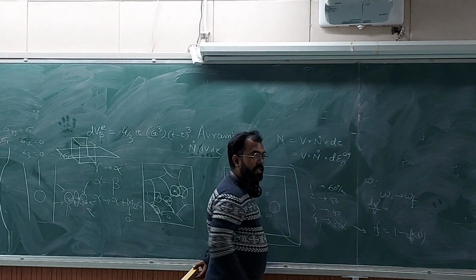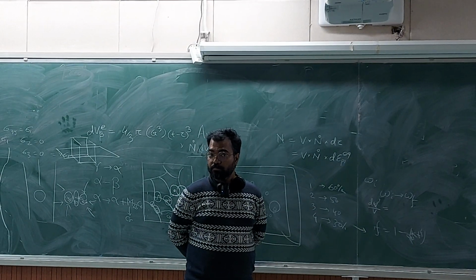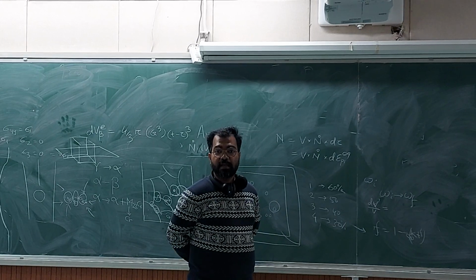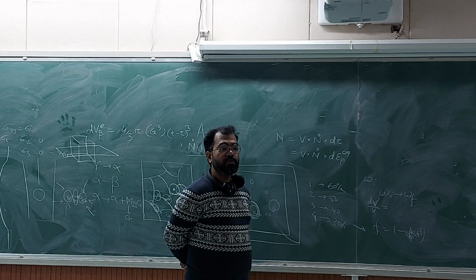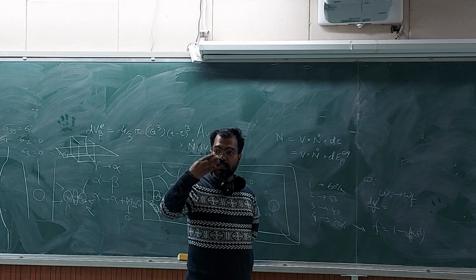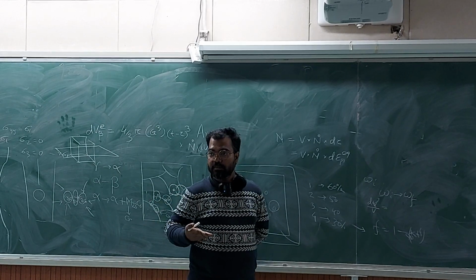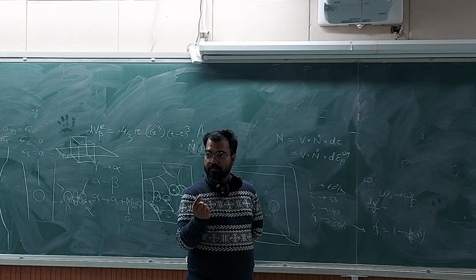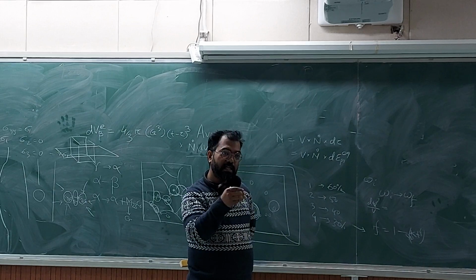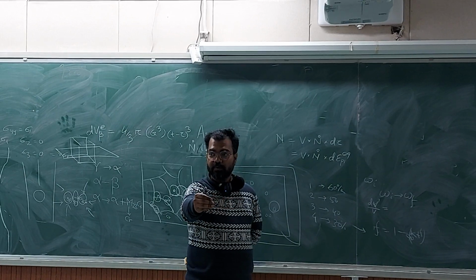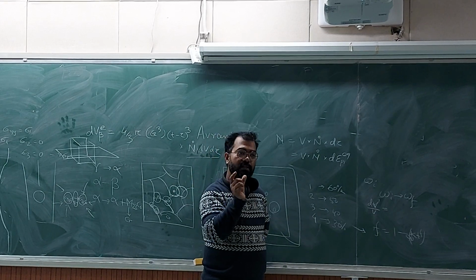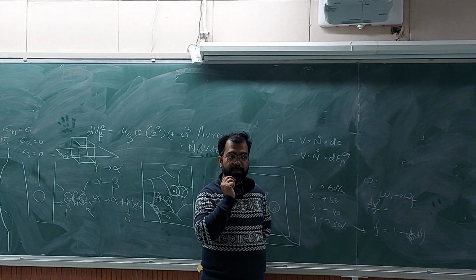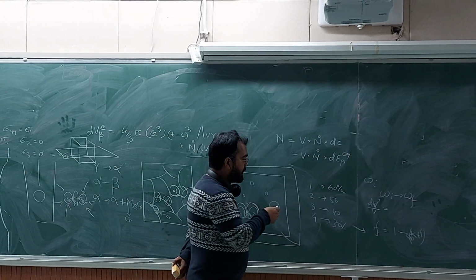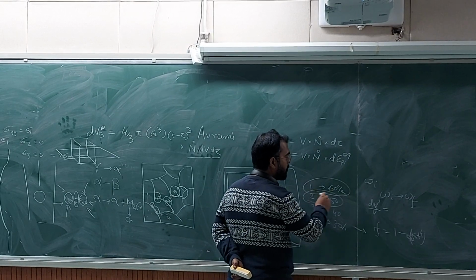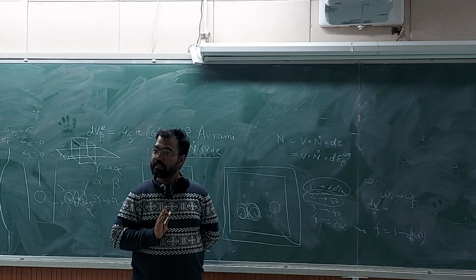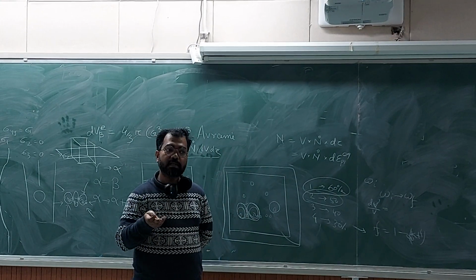So there are, let us say, 4 planes, and all of them have a certain atomic packing fraction. Why will the maximum packing fraction plane be the slip plane? Because on that plane, if you want to move the atoms gradually, step by step, like an extra half plane moving, then you have a lot of atoms on it. So the step will be smaller. The one step, the Burgers vector, which it has to complete so that it goes to the next equilibrium atomic site, is smaller. So less distance, less energy barrier, so the dislocation can move easily. Is it okay? In this case, it is larger, so all the dislocations will be moving on that slip system, whatever dislocation can form on that slip system.